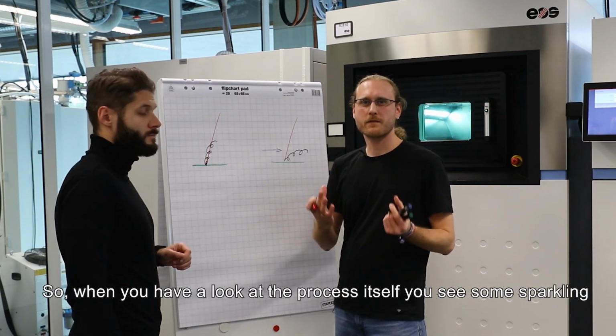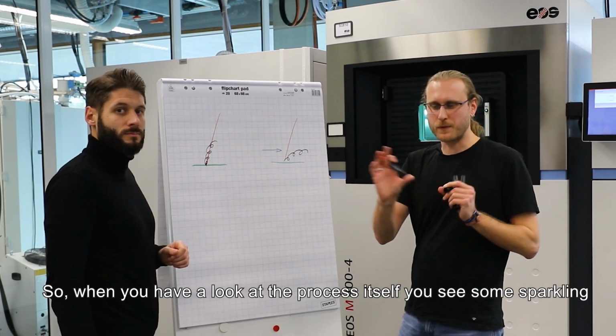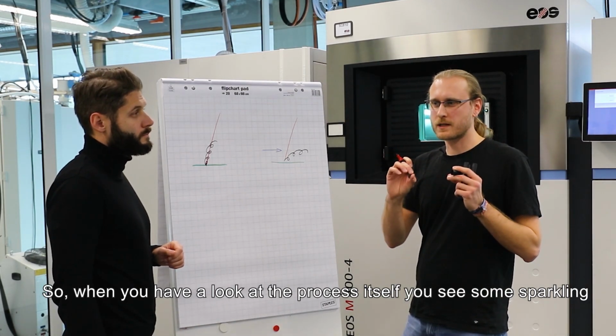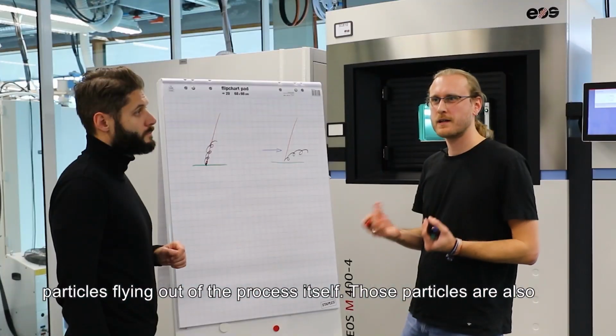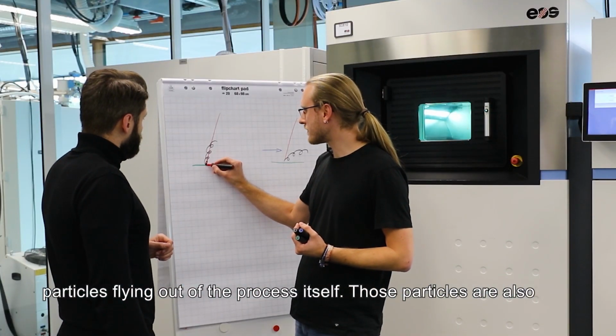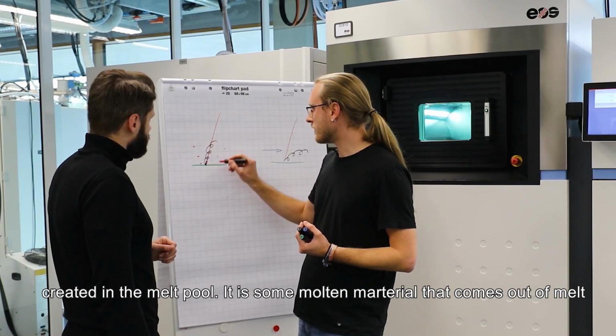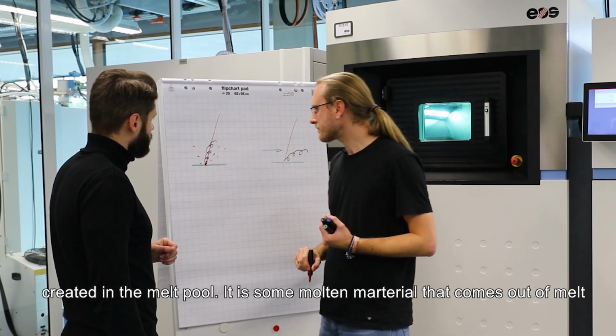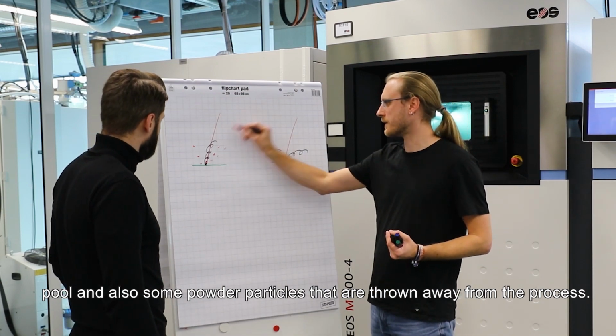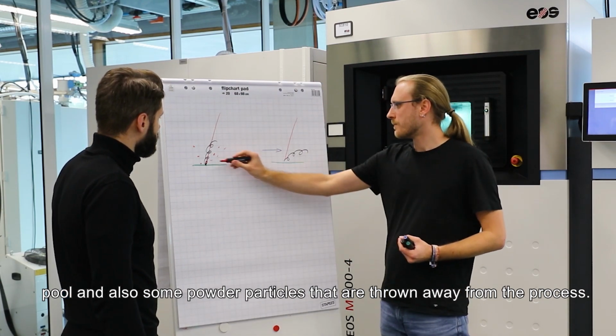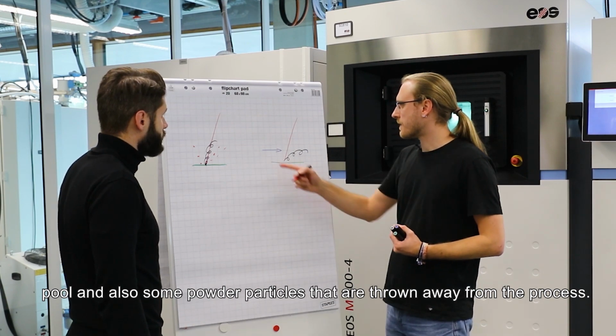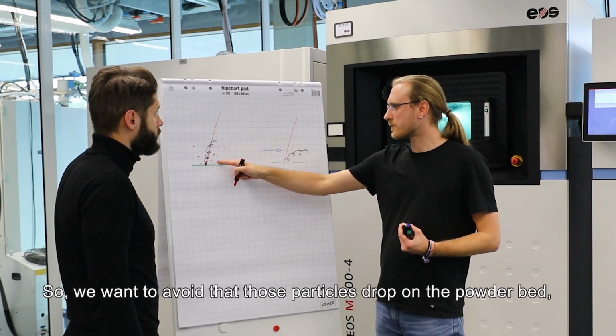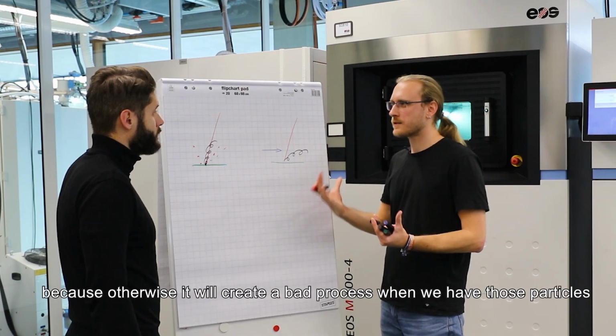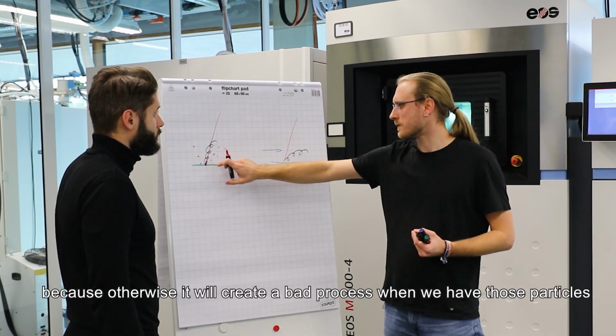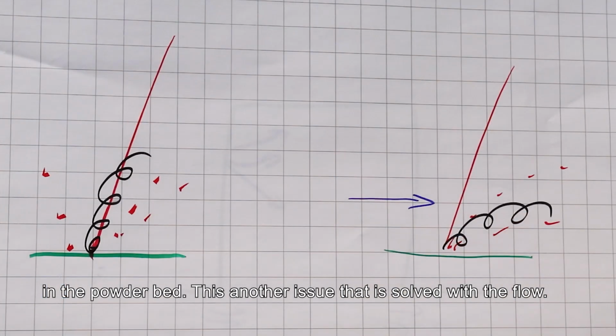and the other point is better. So when you have a look at our process itself, you see some sparkling particles flying out of the process itself. Those particles are also created in the melt pool. It's some molten material that comes out from the melt pool, and also some powder particles that are thrown away from our process. So we want to avoid that those particles drop on the powder bed, because else it will create a bad process when we have those particles in the powder bed. And this is another issue that we can solve with our flow.